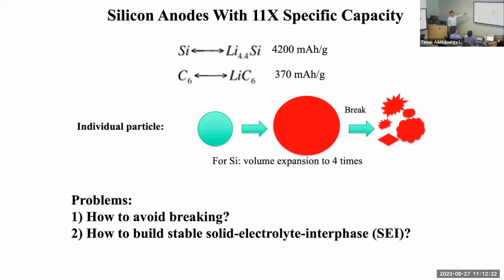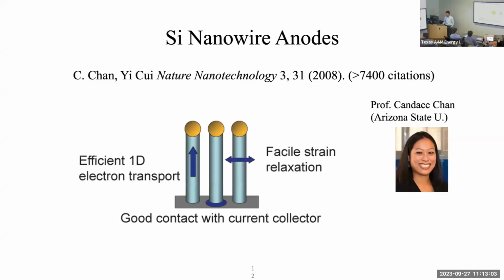But you're facing this gigantic volume change, using silicon as an example. One silicon atom stores 4.4 lithium. Six carbon atoms in graphite only store 1 lithium. So silicon has a 4,200 mAh/g capacity multiplier, but the volume expansion is 4 times. It's gigantic. It causes materials breaking. It causes instability of the interface between this particle and the organic electrolyte. Because volume expansion happens when lithium comes in, and once you discharge, lithium goes out and it shrinks. It's never a stable interface right there. So this interfacial structure will never be stable. This is a killer to the batteries.